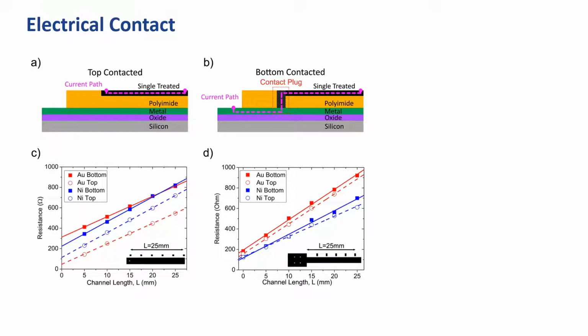Due to their identical formation conditions, the resistivity of the leg is the same in both contact structures, as demonstrated by their identical slopes. Due to their common laser conditions and layer structure, their sheet resistances and consequently their slopes are the same. Where they differ is in the contact resistances, which is extracted from the intercept regions of these plots. However, the distinction between the top and bottom contact structures is the access resistance associated with the contact plug, which we can estimate from the intercept.